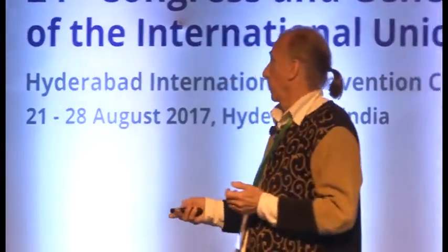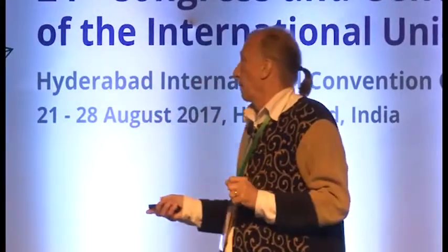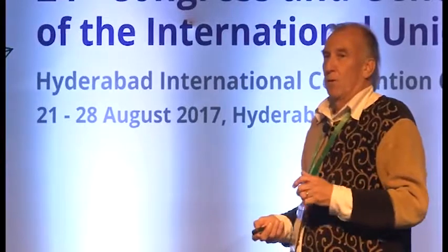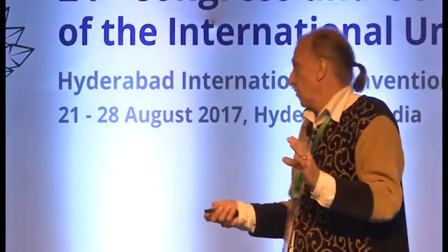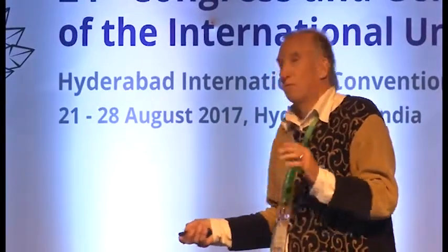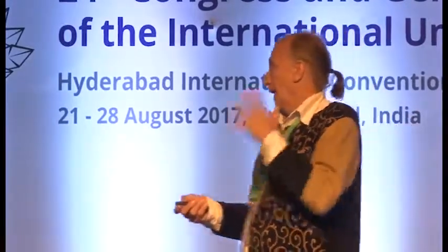I now review key results obtained for molecular crystals, for inorganic organic composite materials, and for natural tissues. First, state of a seed and growing crystals. This here is a key picture of the whole story. It's a model of a seed of 50 molecules long, 10 wide and 10 in the other direction. The molecules are such as iodo-nitrobiphenyl. They have an acceptor part and they have a donor part. They can interact AA, DD, AD, and laterally.